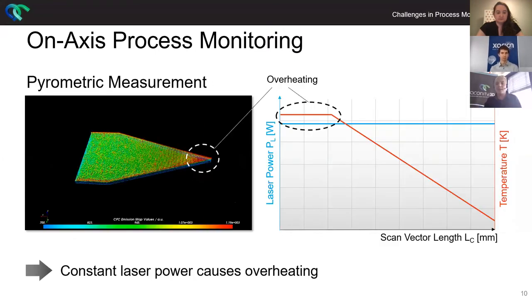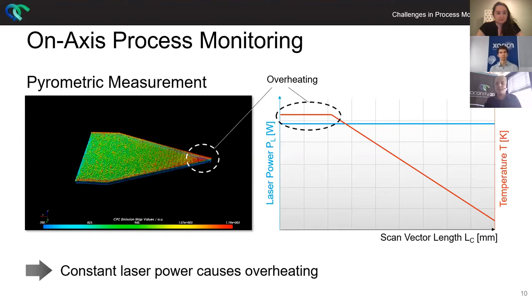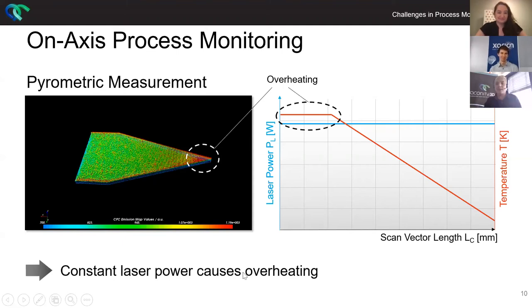What you can do with the pyrometry — as an example for a triangle — we started with the first scan track on the left hand side, which is a little bit colder. As we progress within the part, our scan vectors become shorter and shorter. That translates into an intrinsic preheating effect. With a constant laser power, depending on scan vector length, the shorter the scan vector length, the more pronounced the overheating. That's obviously bad news — first, you've changed the thermal history of your part which may influence your microstructure; second, if your melt pool is hotter, it's most likely larger. So constant laser power in general causes overheating.